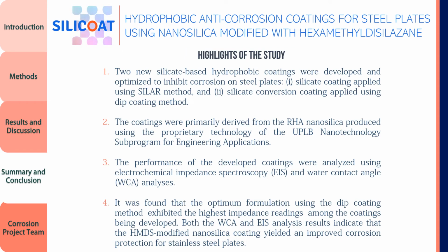To summarize, two new silicate-based hydrophobic coatings were developed and optimized to inhibit corrosion on steel plates: silicate coating applied using the SILAR method and silicate conversion coating applied using dip coating method. The coatings were primarily derived from the RHA nanosilica produced using the proprietary technology of the UPLB nanotechnology subprogram for engineering applications. The performance of the developed coatings were analyzed using electrochemical impedance spectroscopy and water contact angle analysis.